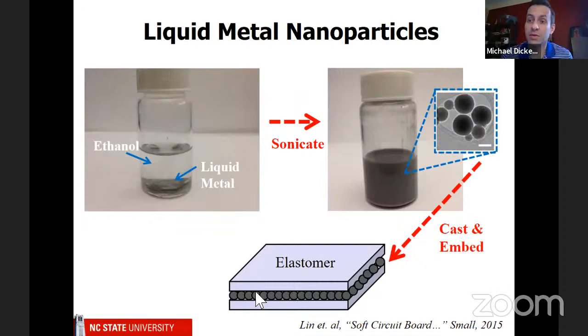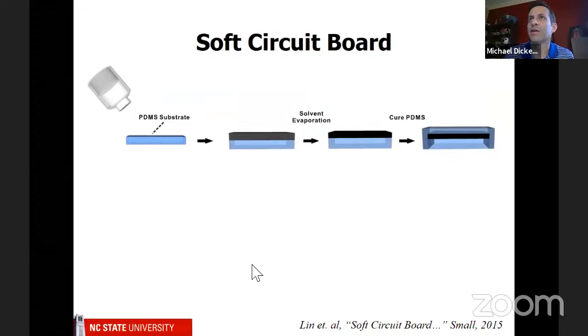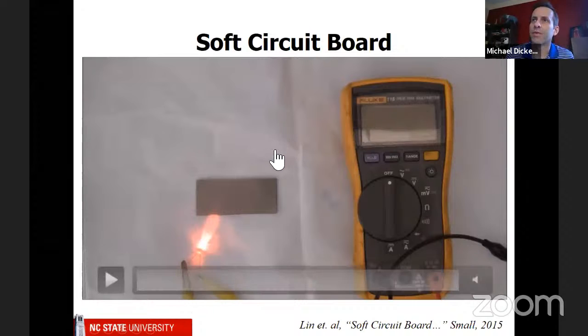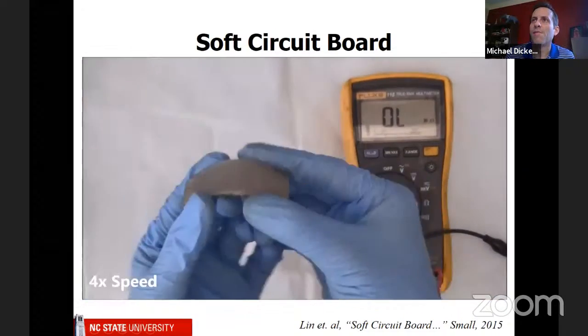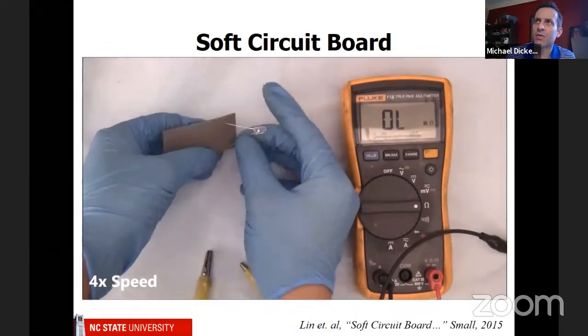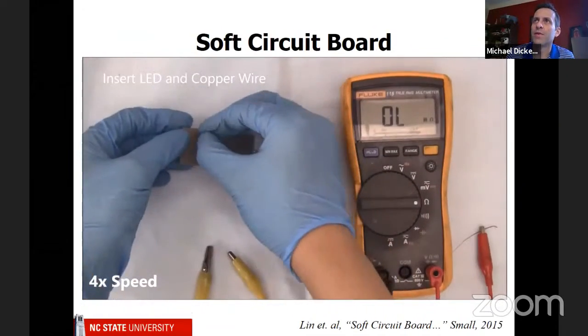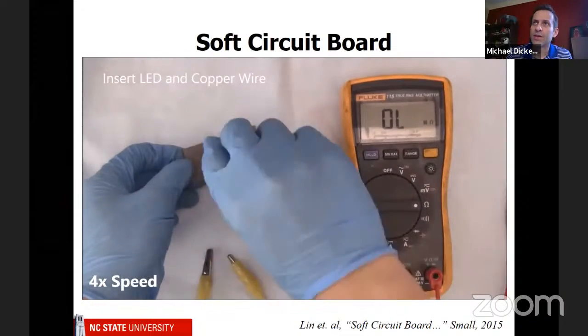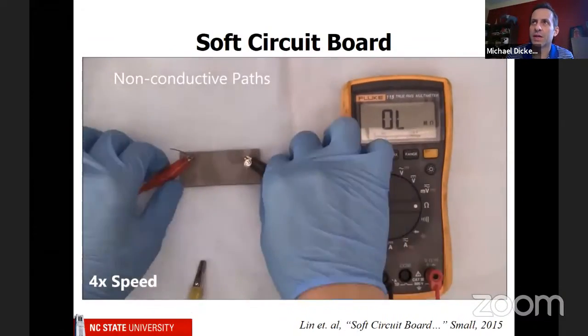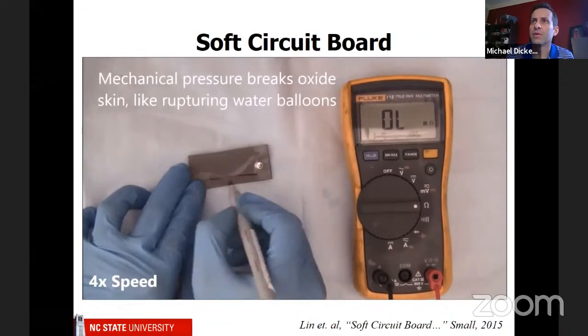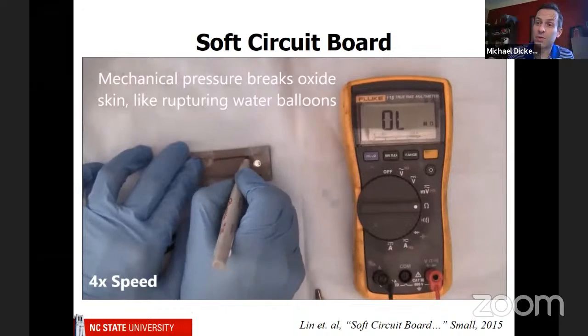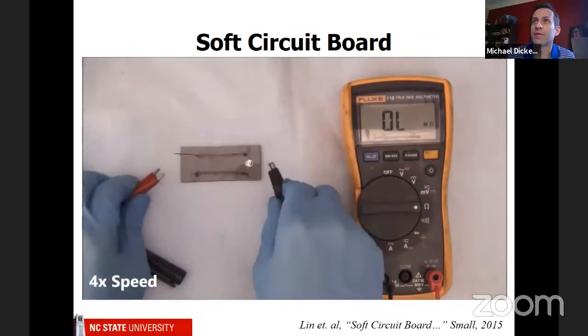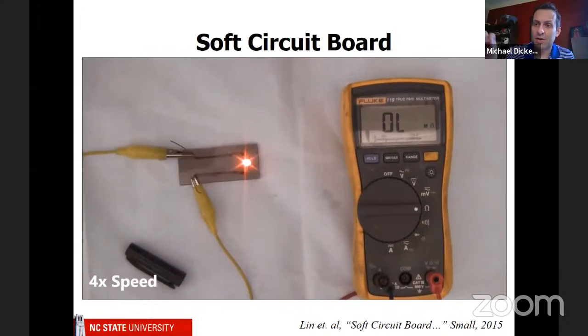However, because the liquid metal is liquid, you can push on it and the particles will merge together. So that's exactly what we did. We took a silicone and we cast a film of it. And we then, well, you'll see in this video, you can stick electronic components into this. So this is just a simple LED and some copper wires. And you'll see that even though there's liquid metal there, it's not conductive. It's very resistive. But if you use a pin to apply some pressure, that will break the little particles. And so now it's conductive. And so you can actually draw this sort of circuit board by hand.